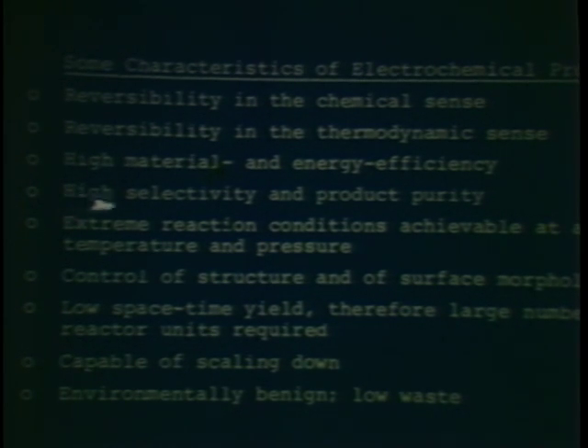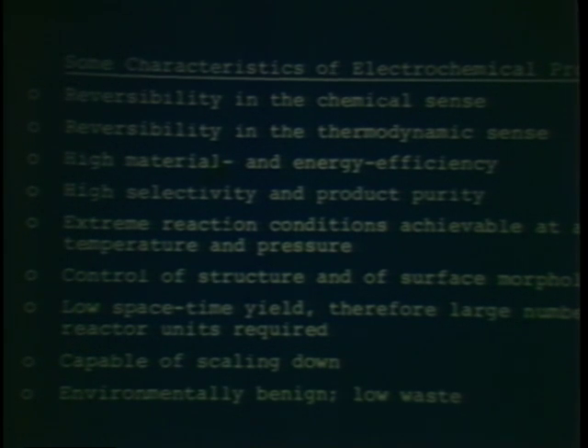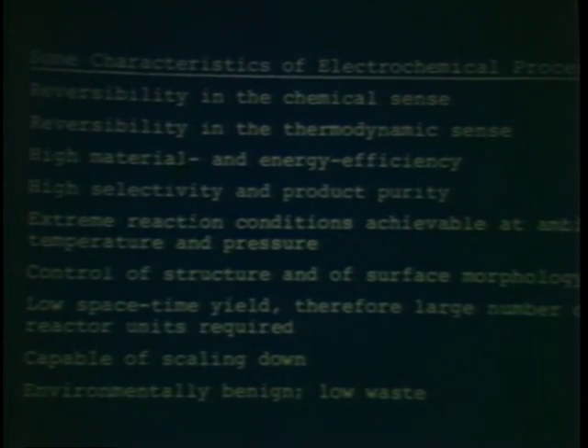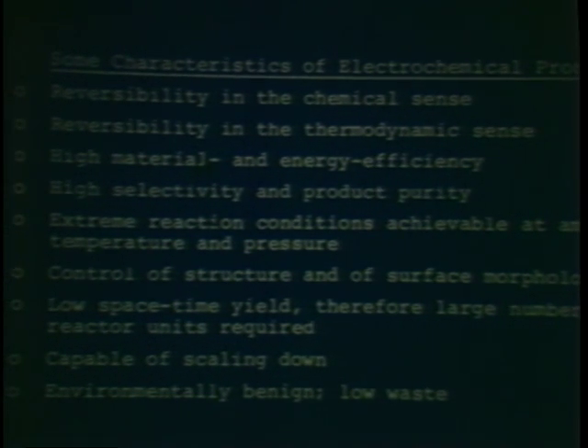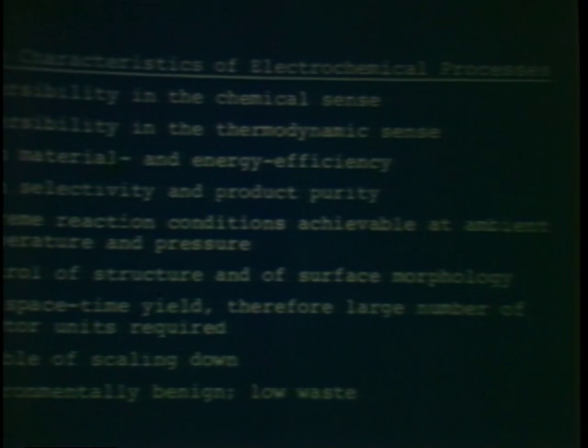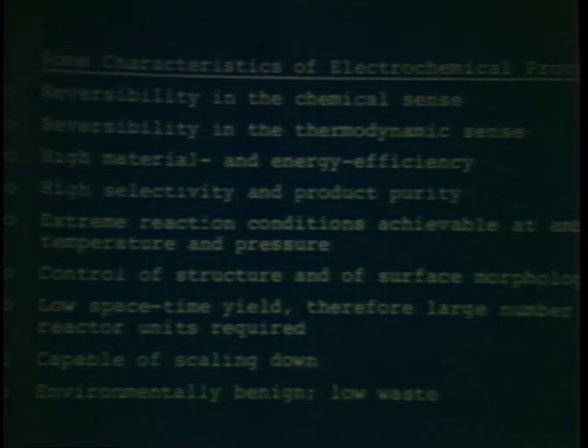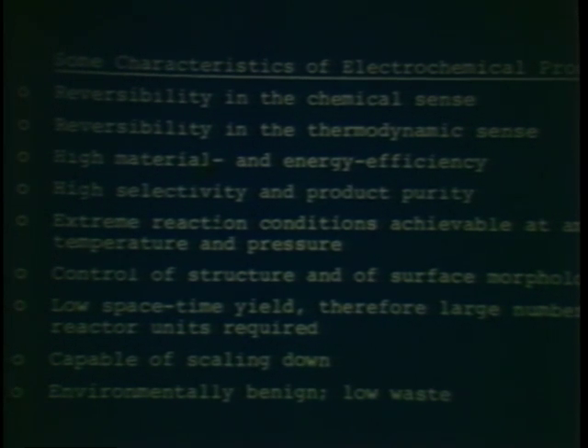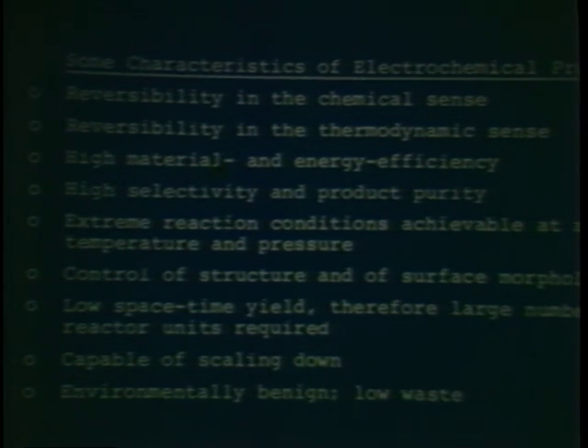They may occur with very high selectivity and purity. A separation factor of 10 to the 6 is not at all unusual in one step. They are capable of extreme reaction conditions corresponding to high temperature and especially to very high pressure. It is possible to generate reduction conditions or oxidation conditions in electrolysis that correspond to 10 to the 30th or 40th powers of atmospheres pressure of hydrogen and oxygen. Certainly no other reaction environment is capable to produce these extreme conditions. And it is, of course, illustrative of this, that fluorine and lithium at the two ends of the periodic table are produced solely, absolutely solely by electrolysis.